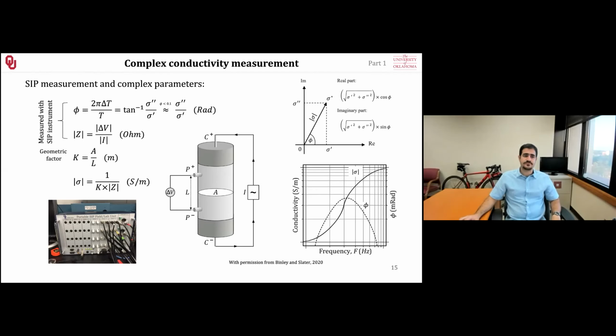milliradian range. Then we have the impedance, which is the potential difference measured at these two potential electrodes, for instance, and the magnitude of the injected current will give you the impedance. Combining them with the geometric factor, which can be very complicated if you have an array of electrodes on the surface, but is super easy for a column, which is area over length, will give you the complex conductivity magnitude.